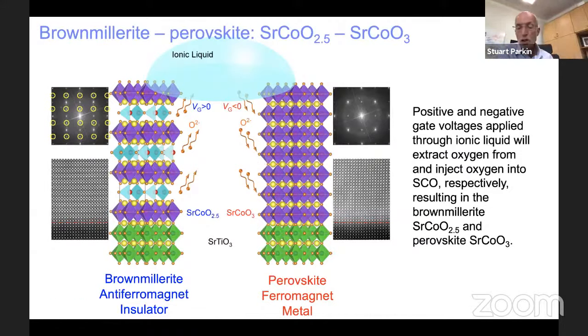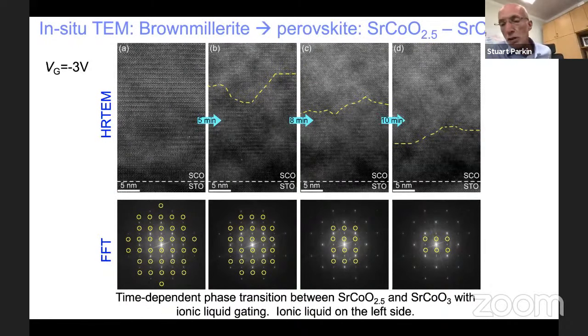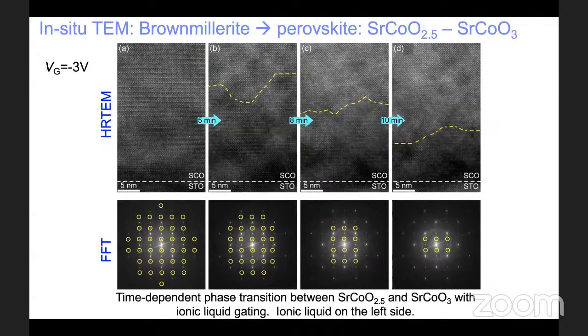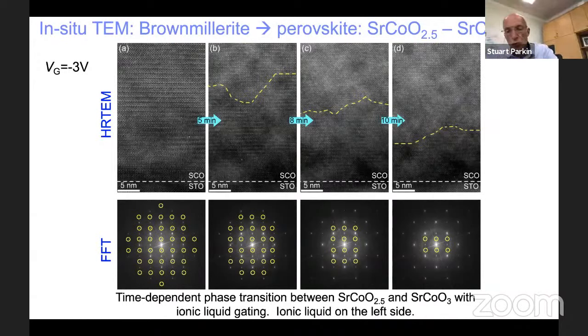So we can switch from one to the other in a non-volatile fashion, as we can see in the transmission electron microscope. On the left, we start off with the brownmillerite thin film, and as we gate it, we can actually gate it completely to the perovskite as shown on the right-hand side. And we can see that also from the selected area diffraction of the left-hand side. You can see the unit cell is much bigger than on the right-hand side. It takes a few minutes, but we can transform the complete film from the ionic liquid at the surface deep into the film.